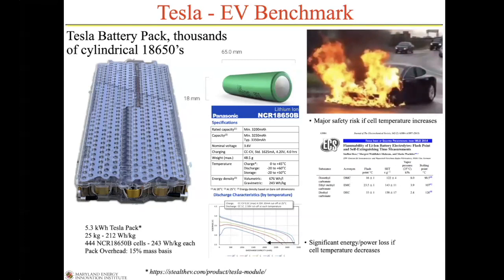And so you also can't go to very high temperature, and you're really limited in the operating temperature of these batteries, so that you don't go too low, so that you get high enough power, and you don't go too high, so you don't have a safety issue. And to do that, not only do you have this mass, what they're doing is they fill it with a liquid which circulates through it, but then to flow that liquid, there's a parasitic power drain.